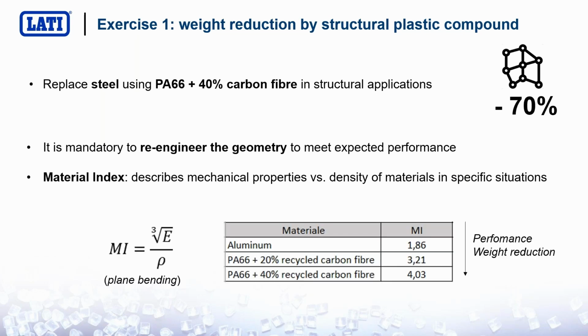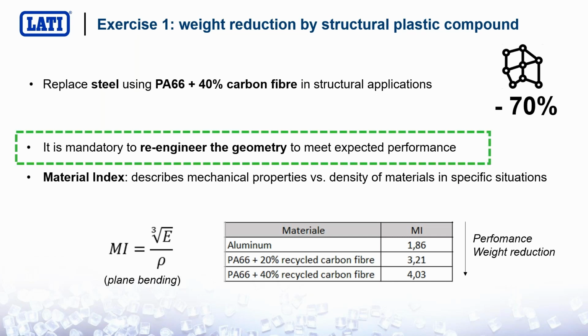And the numbers say that you can have a much more favorable material index when it comes to carbon fiber reinforced plastic versus traditional materials like aluminum. So you will have more strength with lower weight using carbon fiber reinforced plastics. But how does it work? It is mandatory to re-engineer your part. Focus your attention on this topic because it is very important. For structural plastics, you need to re-engineer your part, and this can mean changing the geometry. It is a big effort. It is not easy. It is not straightforward. You cannot use one-to-one plastic to metal replacement in the same geometry. You will have complete failure. You need to redesign your part.